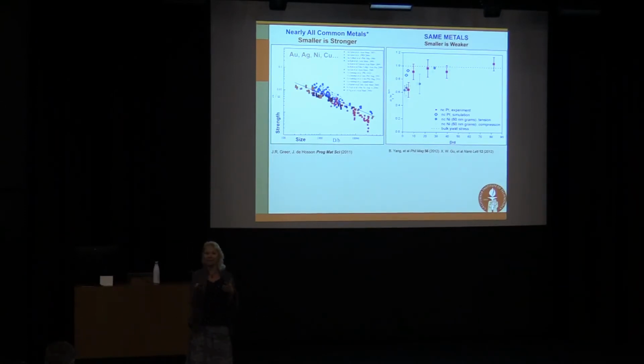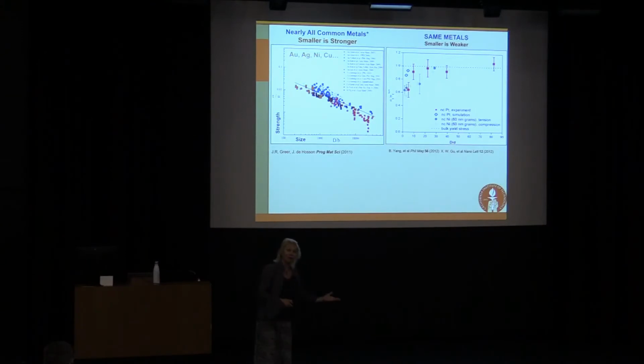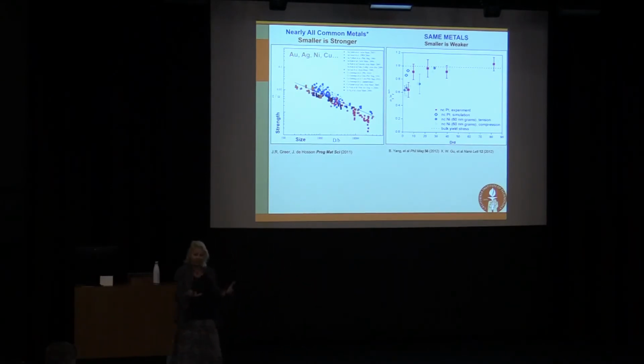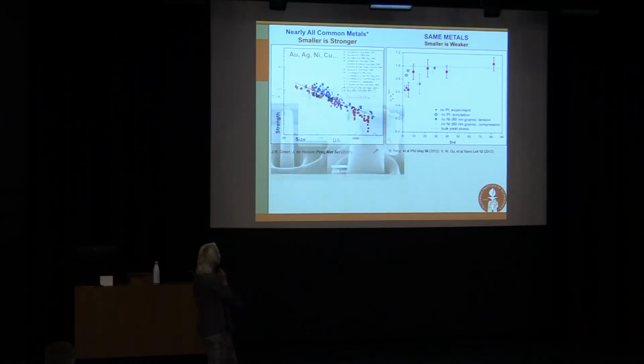So if you use CVD or sputtering or anything else, and now you deposit them as a thin film, all of a sudden this effect is reversed. It's a more modest size effect. It's not a log plot, but smaller is now weaker. And what gives rise to that is that the atomic level architecture is different, because now this is nanocrystalline versus single crystalline. So now you have this powerful tuning knob. You can tune the strength based on the material's dimensions and microstructure. But the size effect is even more powerful than that.